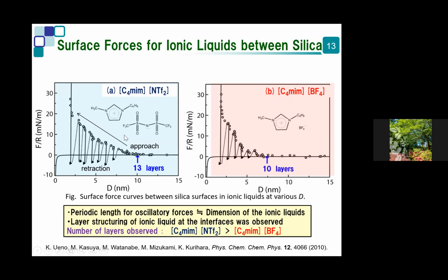If we study the normal force, there is a quite clear oscillation, which means layering. They have a layered structure. But these two ionic liquids did not show such different behavior, although the smaller combination shows a shorter oscillation.